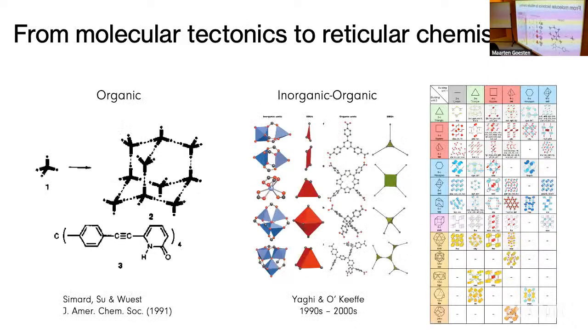to what has now become a very well-developed area of chemistry, especially when people started to move from organic into inorganic-organic systems, where you have coordination chemistry at play. So you have metal sites, clusters here, interacting with organic units with, again, well-defined geometric properties. So typically they talk about connectivities. This has a connectivity of 3. This is tetrahedral. This is D4h. And there are these tables that you can use, which do not always work, I can guarantee you, but they offer a better platform than we have had before.